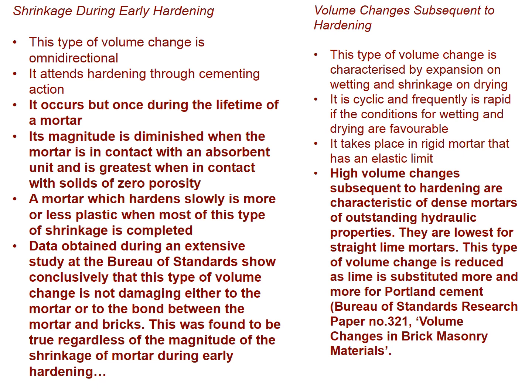This is usually on the next day or the day after that with hot mixed air lime mortars. Data obtained during an extensive study at the Bureau of Standards in the USA show conclusively that this type of volume change is not damaging either to the mortar or to the bond between the mortar and the bricks. Generally speaking, one would add. This was found to be true regardless of the magnitude of the shrinkage of mortar during early hardening.